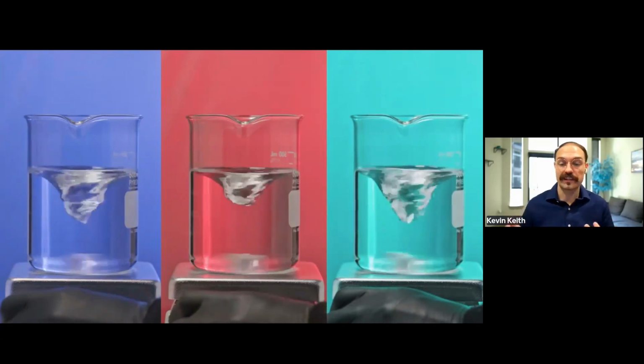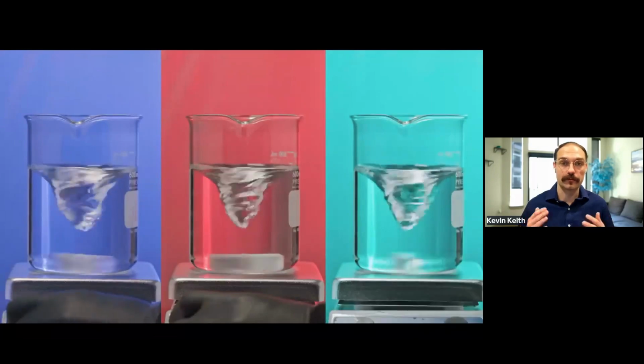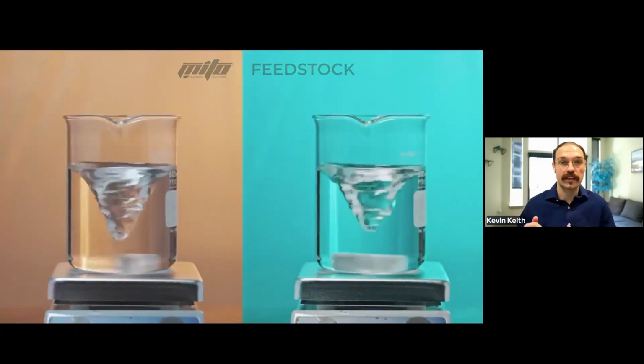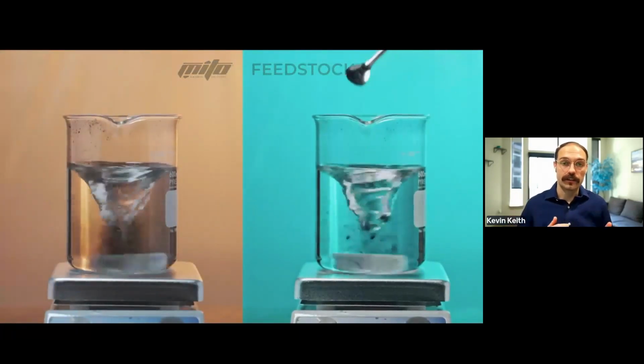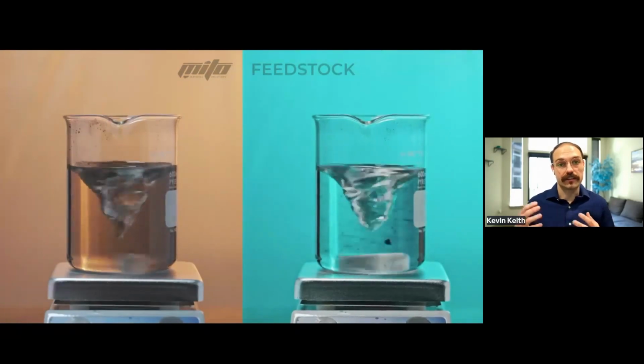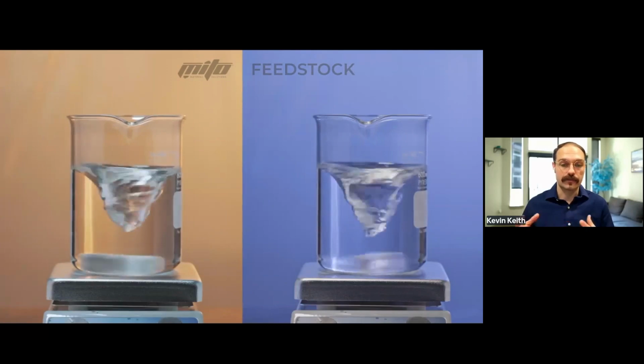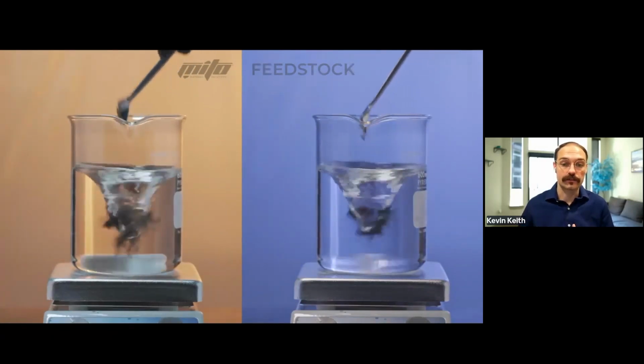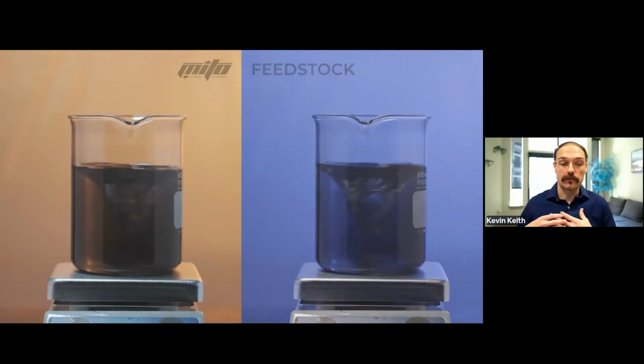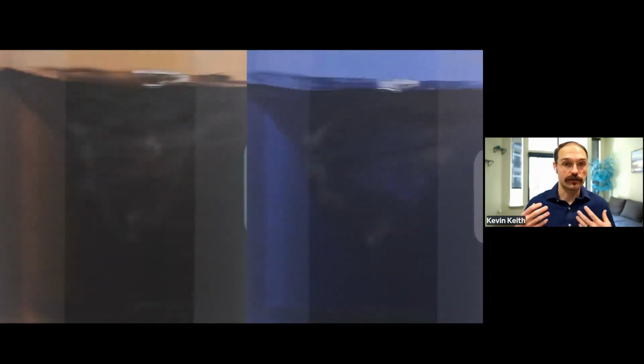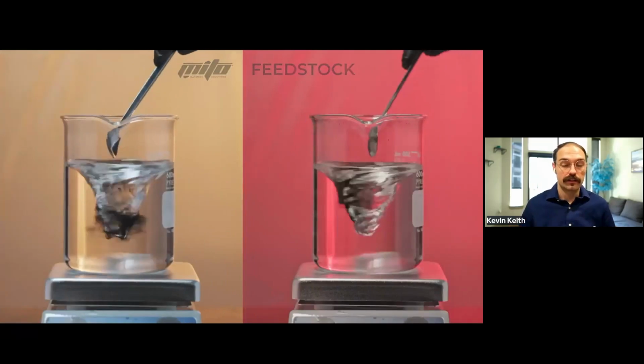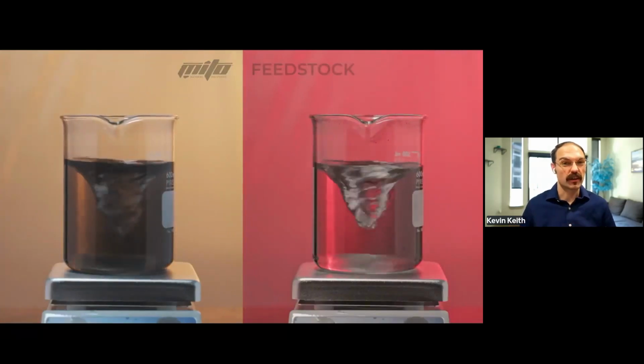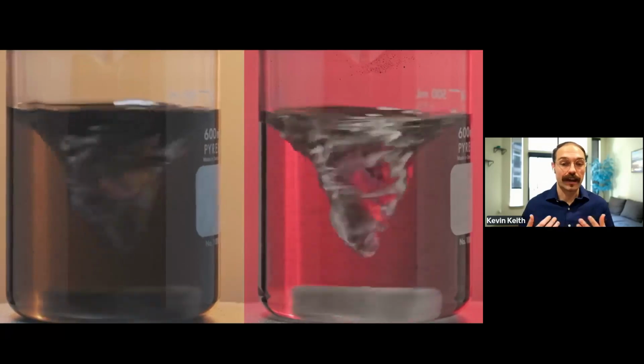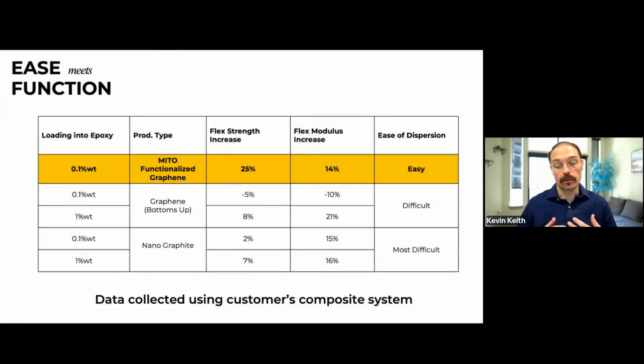So here are 3 different feedstocks made from tops down and bottoms up, so graphite or cracked gas. And on the left in the yellow is our material functionalized on top of that feedstock. So we made a chemistry to go on top of that feedstock. And you'll see here, it disperses much better into isopropyl alcohol using just a magnetic stir bar. This is really unheard of, and we're the ones that have cracked the code to make this a reality in the marketplace.